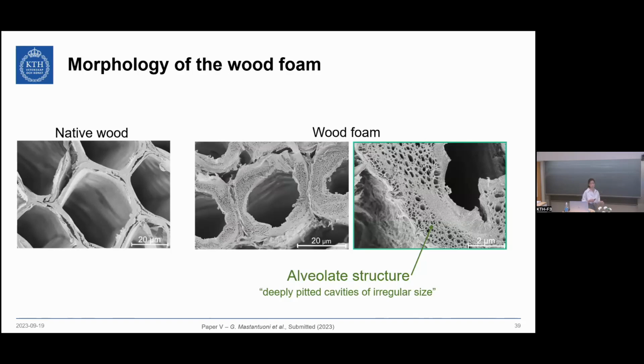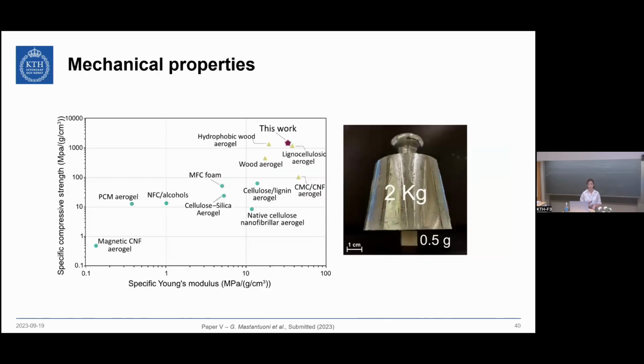And they look a little bit like the structure of bread. The diameter of this porosity is around 100 nanometers, which potentially should be big enough to host bigger moieties inside the cell wall. The mechanical properties of the material were actually very interesting, as it presented the highest specific Young modulus as well as specific compressive strength compared to other foams or aerogels obtained from either cellulosic or wood materials in the literature.